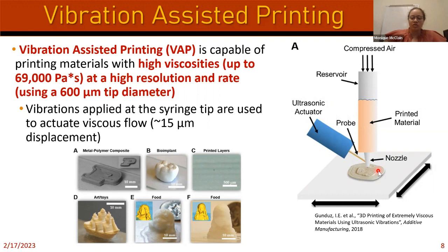So there are several advantages to this technique. In our first paper on this technique, we were really showing what kind of viscous materials we can print with this, and how this process works. For example, we've printed a few different mixtures. This would be aluminum mixed in some sort of epoxy that we deposited or extruded.